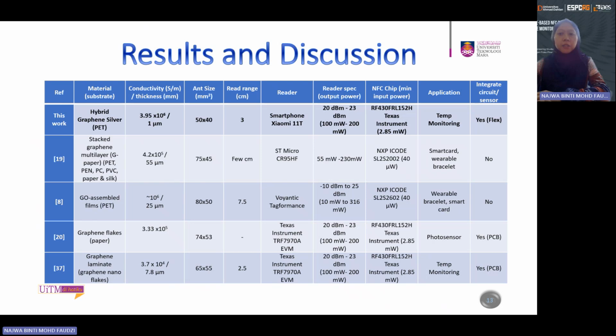The proposed conductive material has been compared with previous studies. It exhibits the highest conductivity value compared to other materials in previous work. Despite its lower printed thickness, it still achieved performance comparable to other graphene-based NFC tags, particularly in terms of the reading range and application. And in terms of the reading range, although it is lower than this reference 8, it still meets the required reading range when detected by a smartphone, typically between 1 to 5 centimeter.